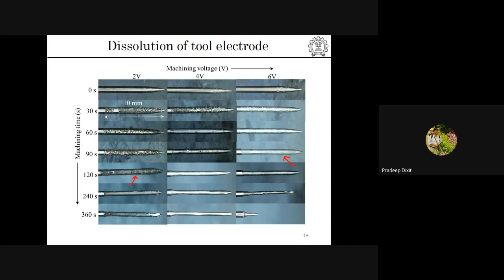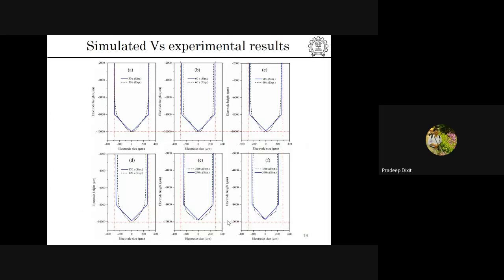At the same time, if you look at 6 volt, from 240 seconds to 360 seconds, this complete part is etched away. So it means you need to use a smaller value of machining voltage. From our experiments, we figured out that 4 volt was sufficient, giving us a controlled electrochemical dissolution.